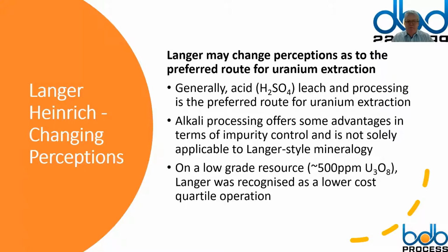and potentially quite a leap for the industry, because alkali really does offer some pretty significant advantages, most notably in terms of impurity control, but also in the potential rehabilitation of the site. We're dealing in an alkali environment, so most of the metals that are problematic in rehab just aren't mobilised in an alkali environment. It's why the alkali route offers the potential advantages it does in terms of impurity in the final product. There are very few metals soluble on the alkali side; there are some naturally, but very few.